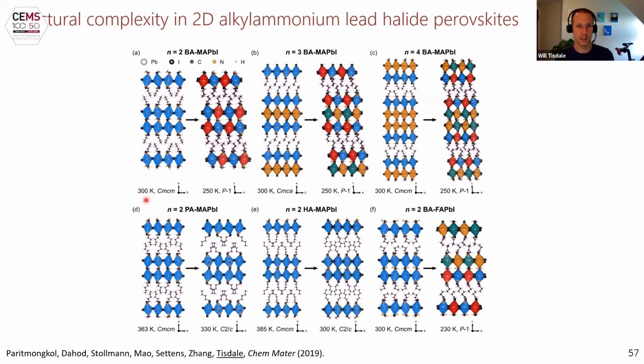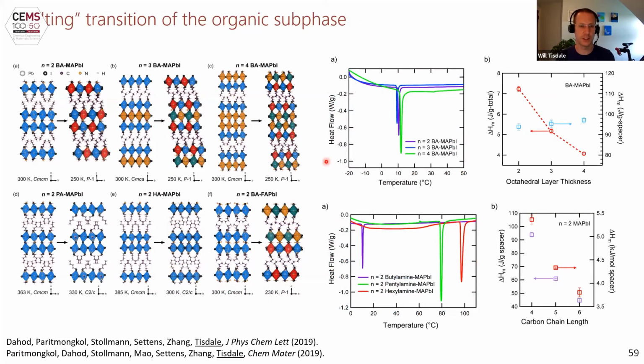All of these are looking at the change in the structure across a near room temperature phase transition that was particularly interesting to us. When we did the differential scanning calorimetry and analyzed the X-ray crystallography on these samples, we identified this particular near room temperature phase transition to be a selective melting or an order disorder transition of the organic subphase. That the organic, just like a self-assembled monolayer or a Langmuir-Blodgett film, will undergo a transition as a function of temperature from a tilted ordered state to a more straight disordered state.